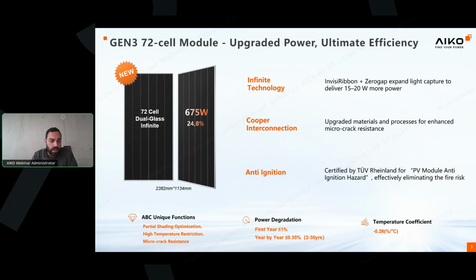It's the partial shading optimization is still there in this panel, the high temperature restriction, and the micro crack resistance, and the lower degradation compared to TOPCon, and the lower temperature coefficient. So I would say all the previous features you are familiar with our panels are already available in this panel, but on top of that, we increase the power with the infinite technology. We have a copper interconnection circuit and the anti-ignition.